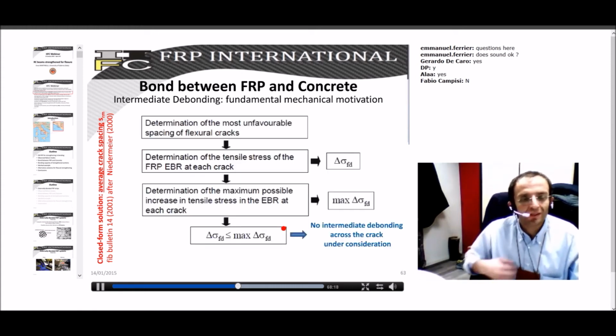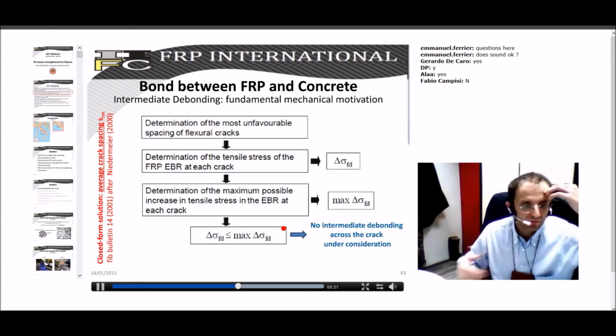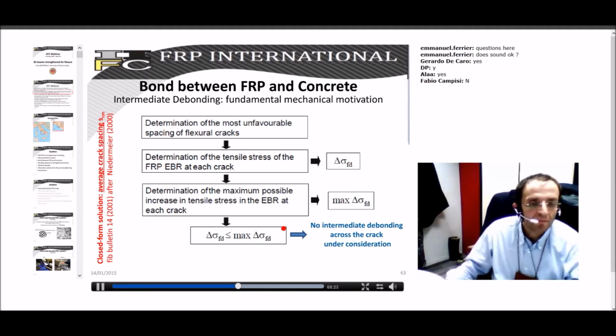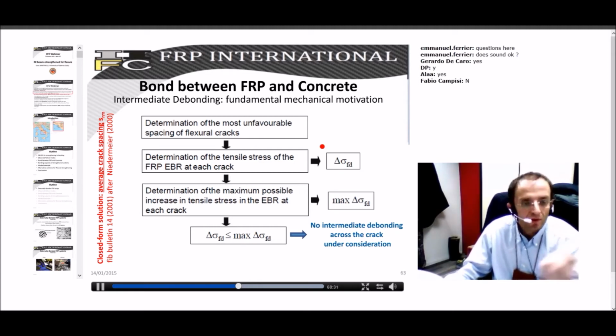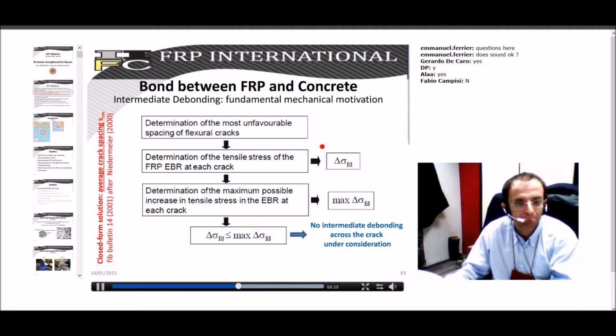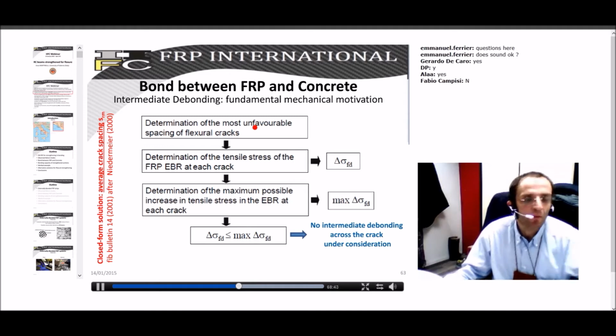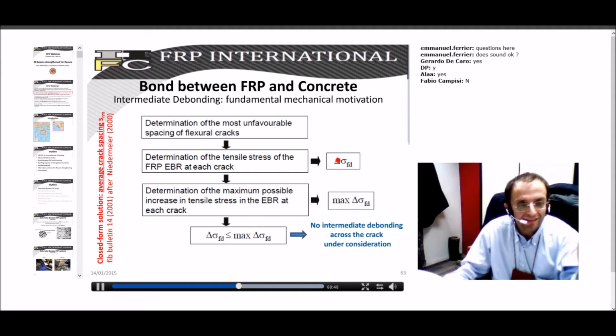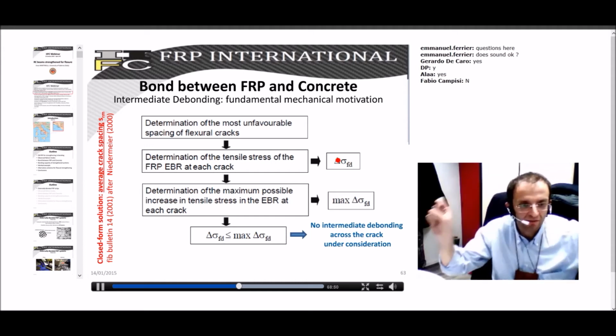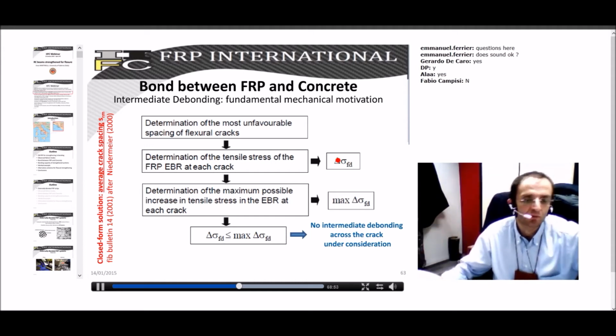So you should evaluate cracks depending on the situation before strengthening. So a possible procedure to check whether intermediate debonding occurs or not should be based on evaluating the actual increase in stresses between two close cracks after having established the distance between these cracks. So you know, or you can estimate, how is the distance between cracks. You can then evaluate the delta sigma, the increase. For each crack, you can evaluate the increase in delta sigma between the two sides of the cracks.